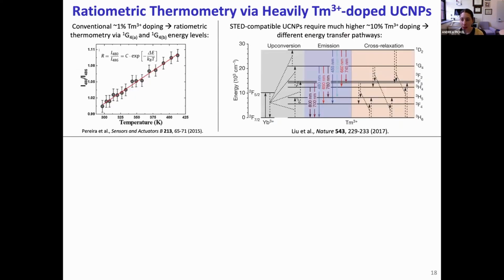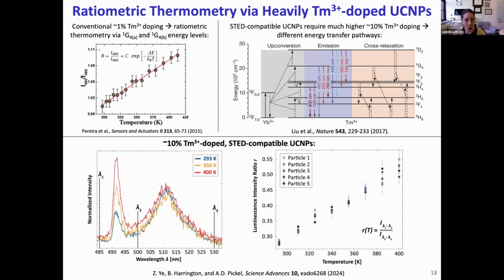From the temperature-dependent spectra I showed earlier, we know that we have a temperature-dependent feature, but we haven't yet rigorously explored whether this approach can enable ratiometric thermometry. And our heavily doped UCNPs have very different emission spectra from conventional lightly thulium-doped UCNPs, and so there was no guarantee we would get a reliable ratiometric thermometry signal. When we plot the ratio of the two peaks shown here for our heavily doped UCNPs, we do indeed observe clear and repeatable temperature dependence with good particle-to-particle uniformity that can be calibrated and employed for thermometry.